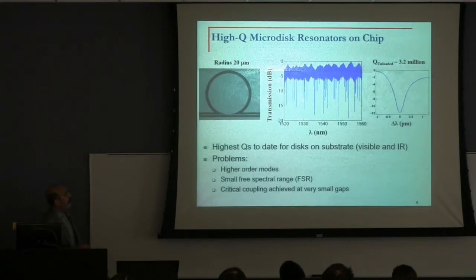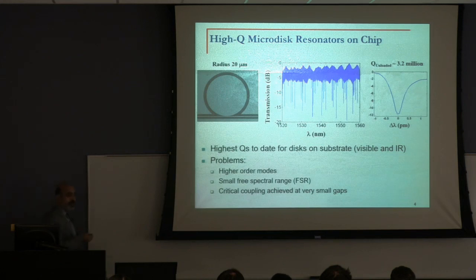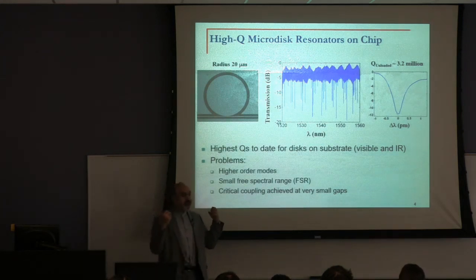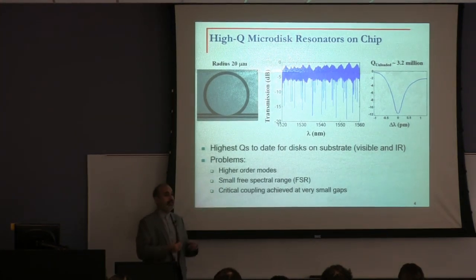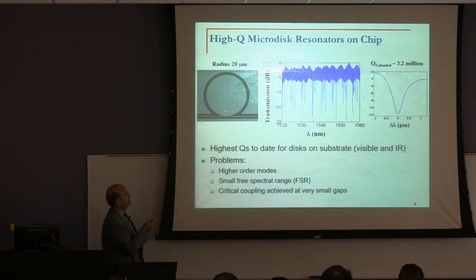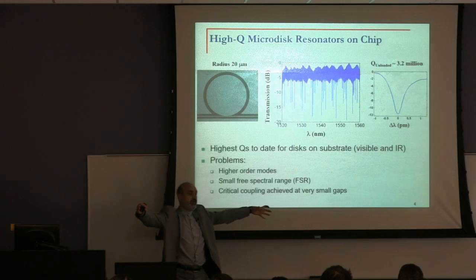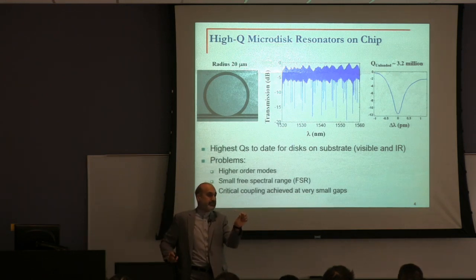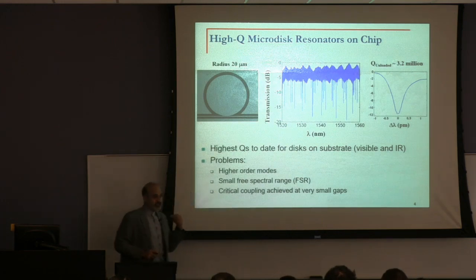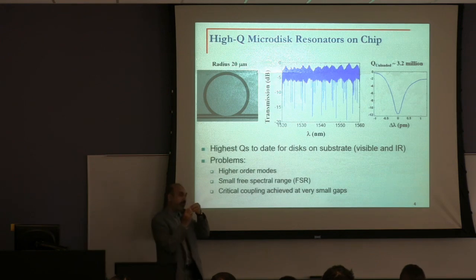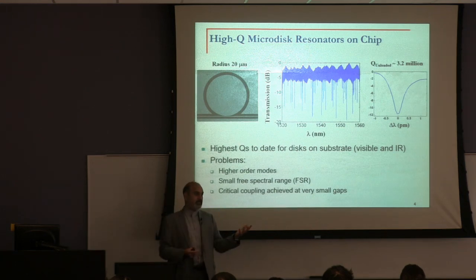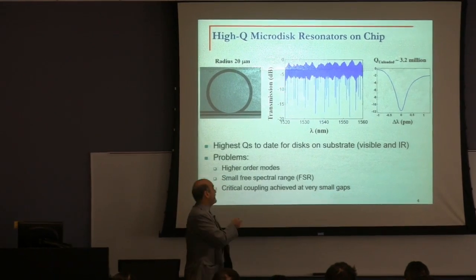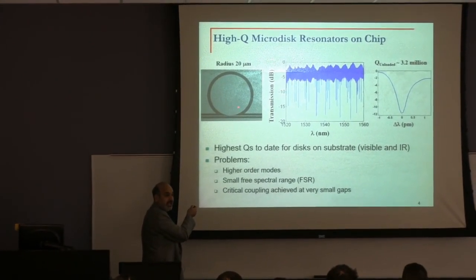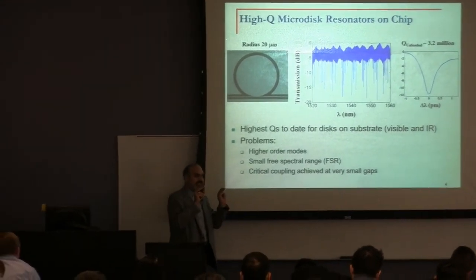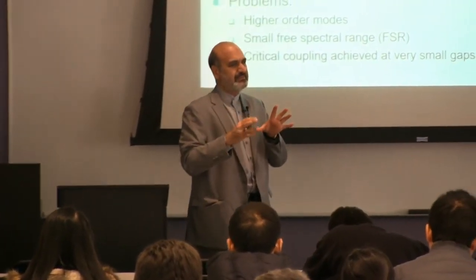well, the key thing is that quality factor by itself shows how you can confine your mode inside the structure and therefore build up energy inside that. But then the question is, is your energy built up over hundreds of microns or over tiny nanometers? The key thing at the end of the day is energy density, which is number of photons per unit volume. Now, two properties have two different aspects of this story. Quality factor is about the confinement of energy, putting it more and more in the resonator. And then mode volume, which is in essence the volume that your mode occupies, normalized by the index of refraction.